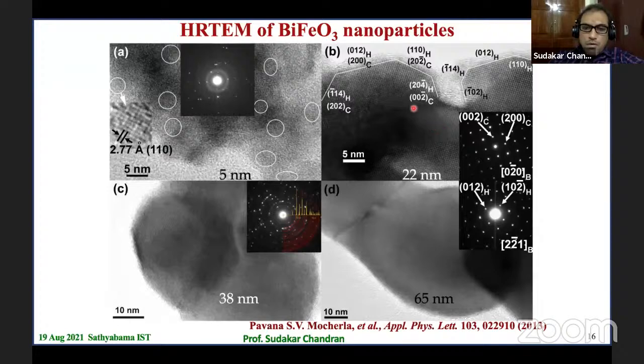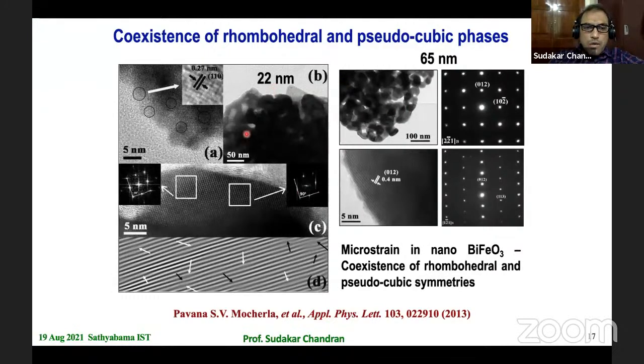But then specifically around the crystal size of 20 to 30 nanometer, we do observe a lot of local strains. You can see that in the fast Fourier transform image that we obtained from this high resolution TEM image, there are lattice planes that are pulled apart, and the same set of lattice planes in some other region are pushed. They are all pushed close to each other. So there are tensile and compressive strains within the lattice, and of course, these kinds of strains go away as you go to very large sizes like 65 nanometer.